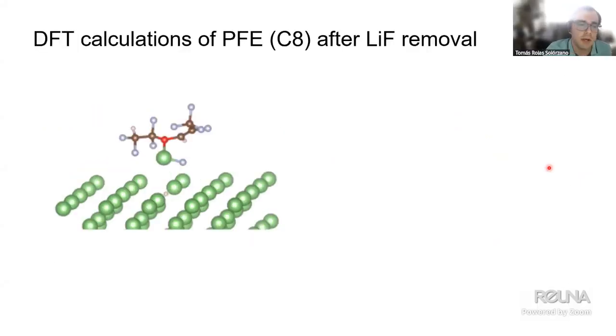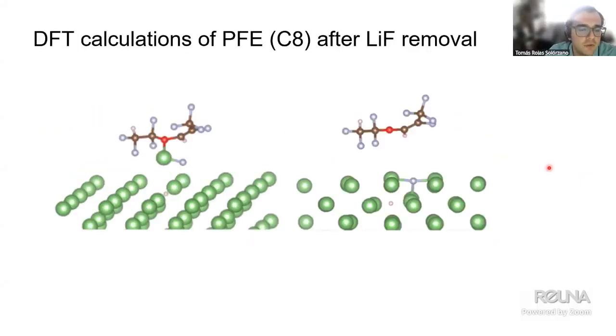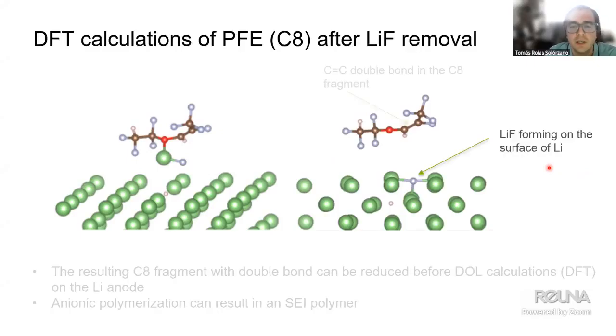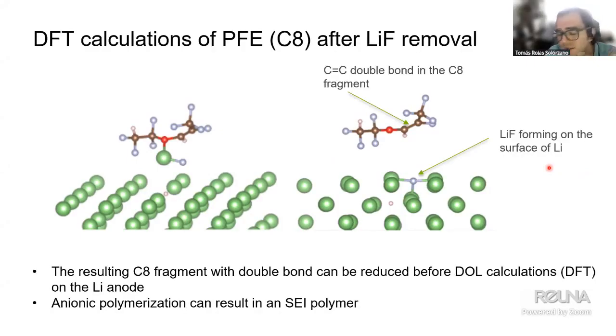We then combine both of the configurations after the replacing that we did, placing the molecule where we took the hydrogen and replaced it with the lithium. We place it over the surface in which we replace the lithium with the hydrogen and simulate this system as a whole. And what happens is that the lithium easily gets removed from the molecule, goes back to the surface, and not only that, but carries one of the fluorines from the molecule.